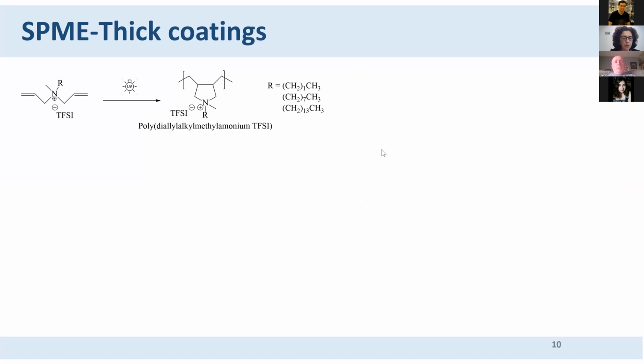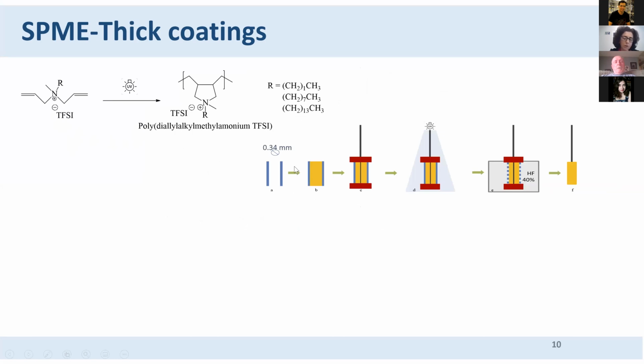So David took advantage of the work that we were doing in gas separation membranes, and he used the polydiallyl alkyl methyl ammonium TFSI, with several alkyl chains. So the way that he did it was we had a mold, and we filled the mold with the solution with the polymer. We put just a handle, and then we took it to the UV curator. In the end, we just dropped this mold, which was made of glass, in an HF bath to dissolve the mold. And here we have our fiber. So it was quite simple to prepare.